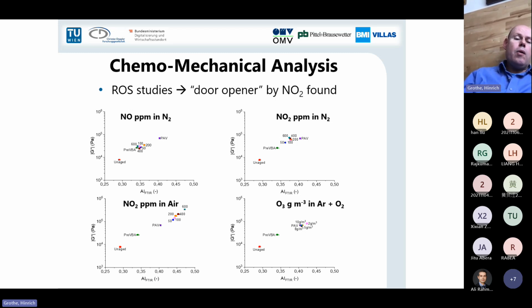When we work here in our Vienna binder aging cell, just with pure nitrogen monoxide, there is not so much aging observed. It's much below the pressure aging vessel test. It's probably only thermal aging. When we apply NO2, it's also not so much reaction because it's NO2 inside nitrogen. If we apply ozone, which is a strong oxidizer, we go beyond that already a little bit. But if we apply NO2 in air, this is really changing. And obviously, as a reaction mechanism, it needs a nitrogen oxide, which is a radical, but it needs nitrogen oxide in combination with oxygen.